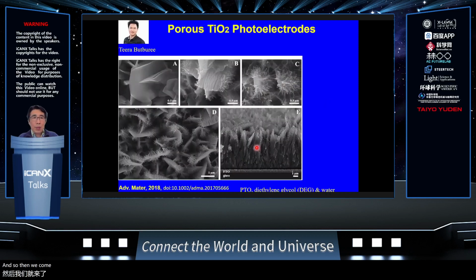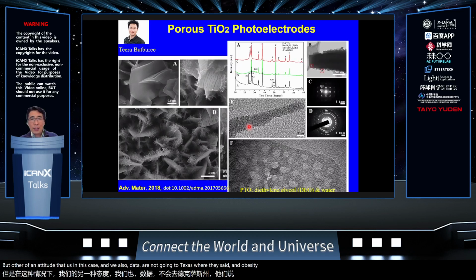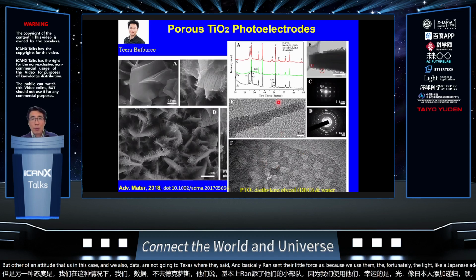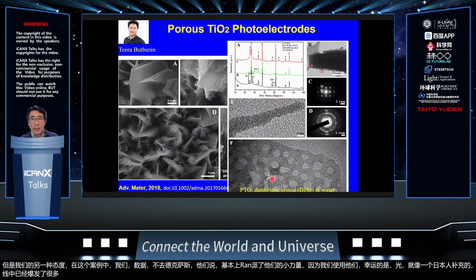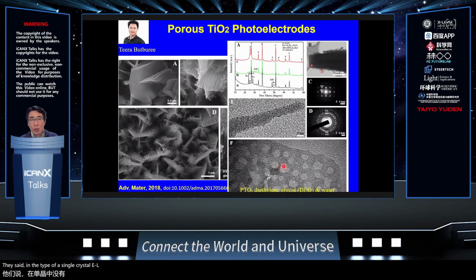We came up with another approach, still using TiO2 as the example, but we used a hydrothermal process to prepare the TiO2. This material still has a layered structure, but it's not packed in parallel onto the electrode surface; it's vertically grown onto the electrode, on the FTO glass in this case. We also did a number of characterizations, and we understand there is a lot of porosity. That's because we used protonated titanate as the precursor, and when we do acid etching, we can generate a lot of porosity inside. This type of single-crystal porous structure is very helpful for charge separation and transfer, because the pathway of the charge carrier can be very short to reach the surface.